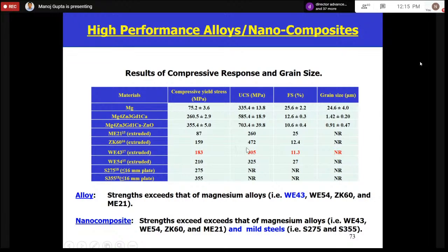So what is the importance of this value 260, 585? Because now these values exceed certain very high-end commercial alloys used in aerospace application like WE43. So you can take this composition, build your own alloy. Now you see the magic of nano reinforcement, which is zinc oxide in this case, and now you get the values 355 megapascal, 703 megapascal in UCS, failure strain still remaining 10% and higher.